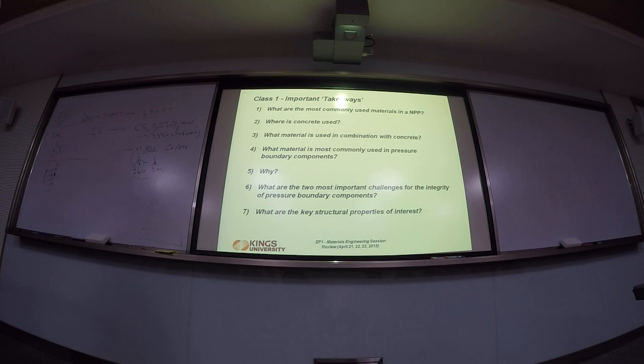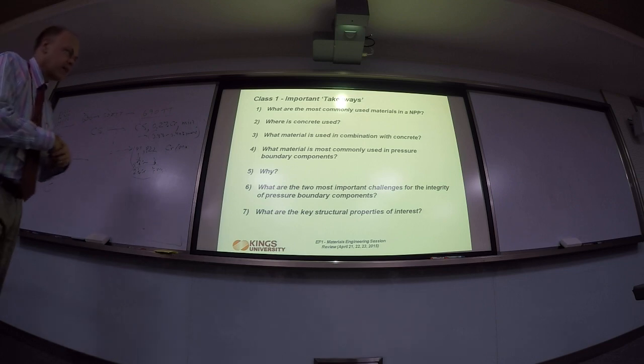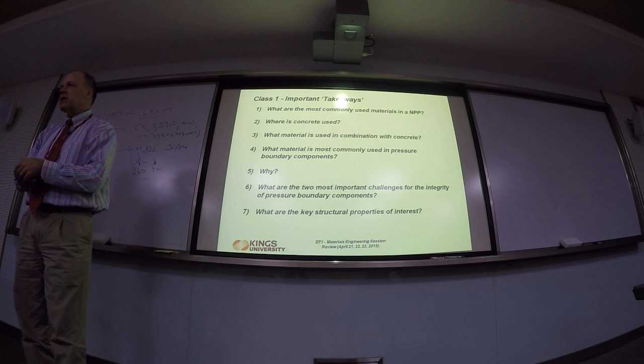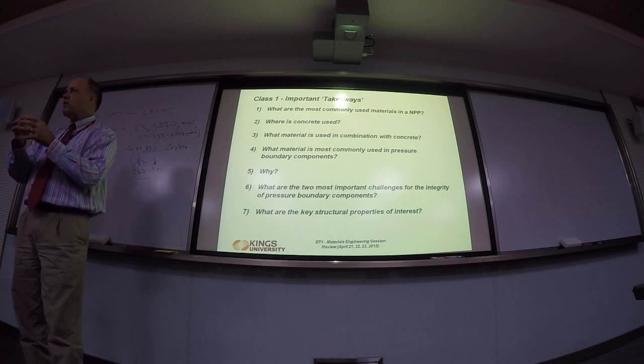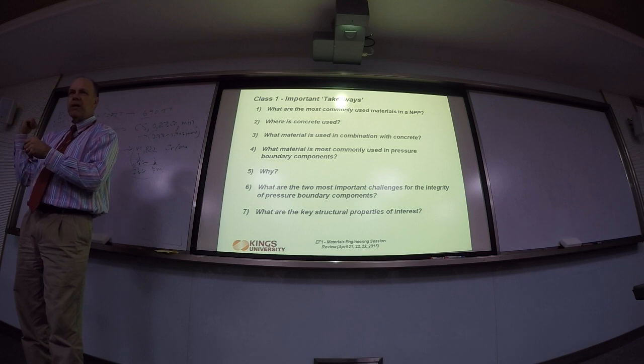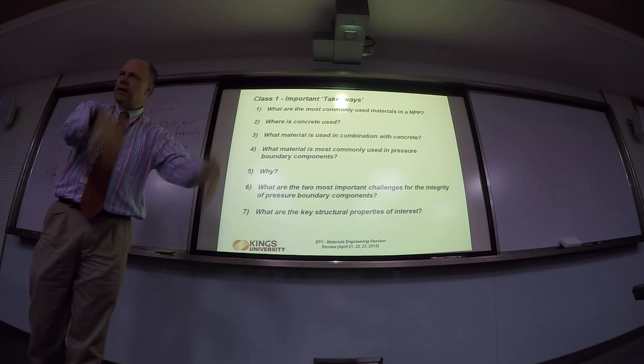Pardon? What happens? I melt it, right? I put in energy, electrical energy. Sometimes I have a welding rod that melts, but there's so much heat. This side melts, the welding rod welds, and they all come together and they fuse again, right? But when they cool off, the chrome doesn't always stay equally mixed like from the steel mill. And so I can have chrome precipitation out, carbide precipitation. We don't get that so much with carbon steel. Carbon steel makes a good, solid weld that doesn't crack. But chrome moly and stainless steel, we don't want to use those if we don't have to.